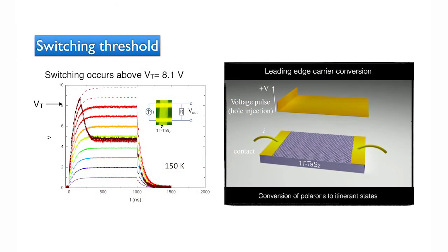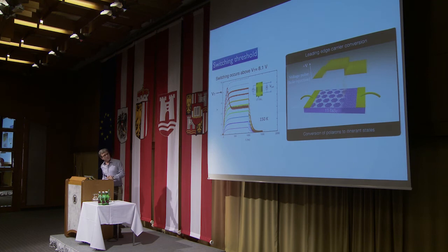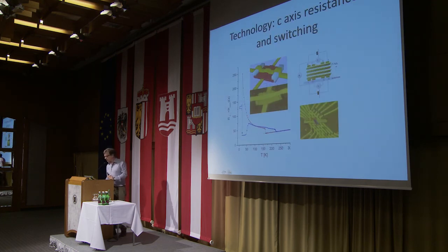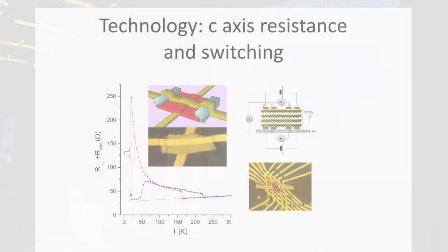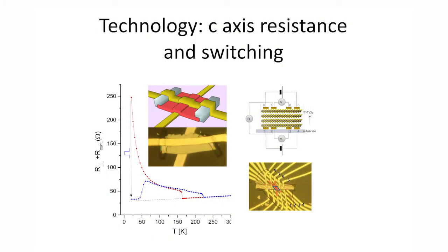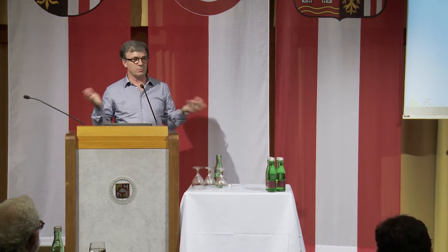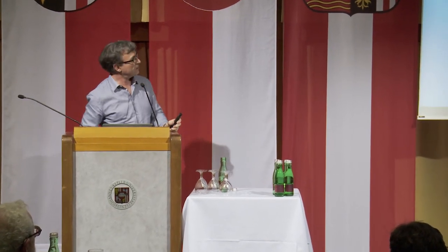Okay, essentially, as you apply a pulse between the electrodes, it converts it from a uniform polaronic crystal to a patterned, textured polaronic crystal. Okay, and now to finish off, it works also with c-axis. This is a technologically very important issue. It doesn't matter whether you put contacts sideways or on top of each other. That's very important technologically. It works both ways.